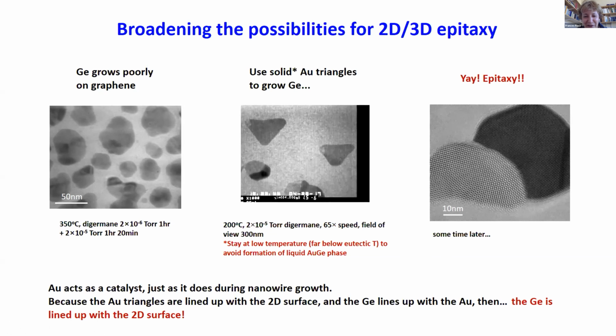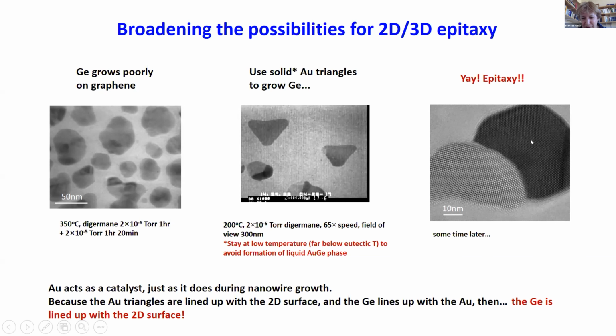Do you see that little gray area that just appeared? And another one's going to appear just here. Wait for it, wait for it. There you go. So the gold is catalyzing the deposition of germanium. Because the gold is attached to the graphene and the germanium is attached to the gold, then the germanium has an epitaxial relationship to the graphene.